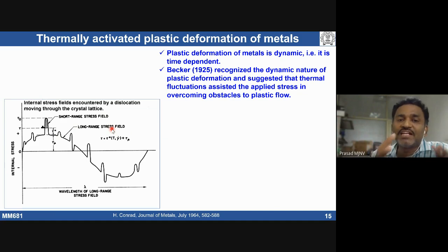The obstacle size, if it is more than 10 atomic diameters. If you take a particular material, we know the atomic radius of that metal, so the size has to be at least 10 atomic diameters. That basically involves a long range stress field. If the obstacle size is less than 10 atomic diameters, that involves a short range stress field. So two different types of obstacles are going to be present.